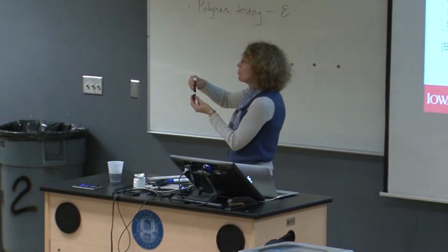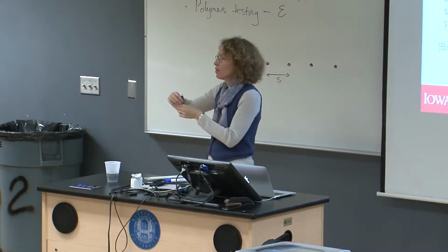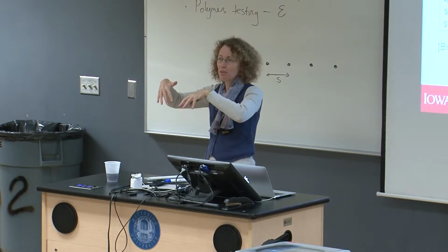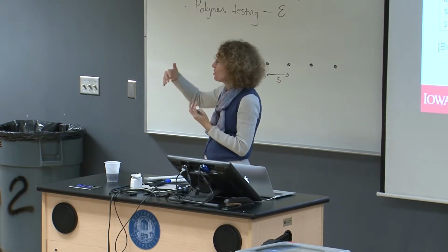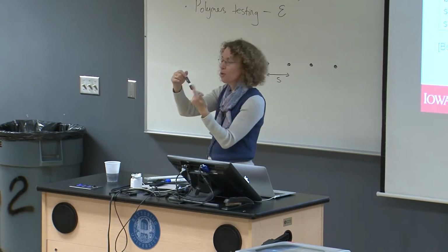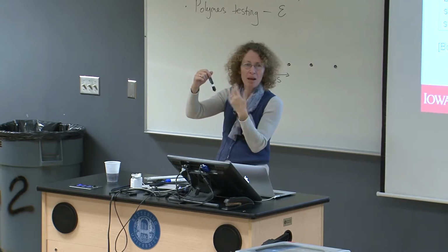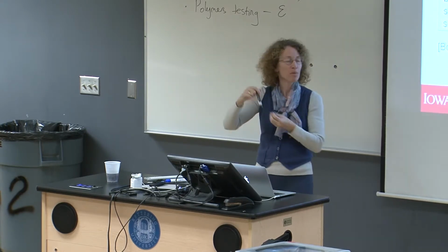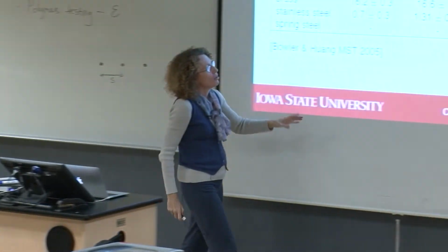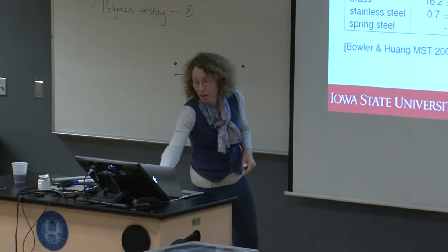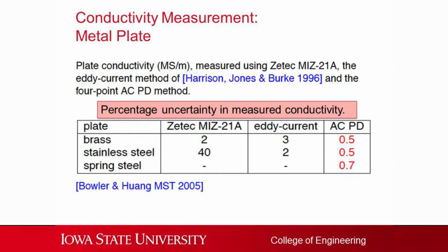It's actually more difficult to characterize a coil setup than it is to characterize a 4-point setup. The 4 points are just a simpler probe. With a coil, you have to worry about how many windings there are and the fact they wobble a bit, things like this. The bottom line is we can get better accuracy using the 4-point probe. So this is the percentage uncertainty in our measurement.